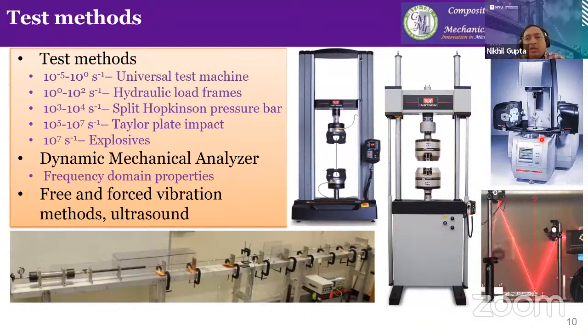Apart from that, there are other methods like DMA, dynamic mechanical analyzer. This equipment is based on the vibration response. Then there are free and forced vibration testing methods, then ultrasonic imaging methods, all of which can provide you some measure of modulus, if not the direct modulus, and they can be used. Now, think of also the complication that you need the data at high temperature. So you need furnaces mounted on these methods. And high temperature Hopkinson bar testing is really a very, very difficult area where you need to apply compensation factors for the bars which are used to obtain the data. And those fields are never easier to deal with.